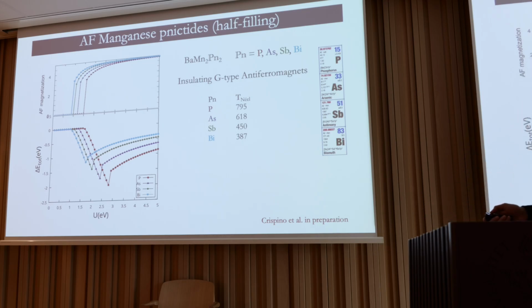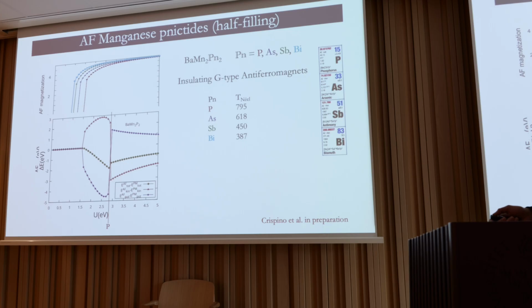You really see that you have 2 regimes in each one of these color lines, so for each one of these compounds - a regime beyond this line and below this line, now for instance for phosphorus. And if I look at the differences in kinetic energy and potential energy, you really see that these are weak coupling versus strong coupling.